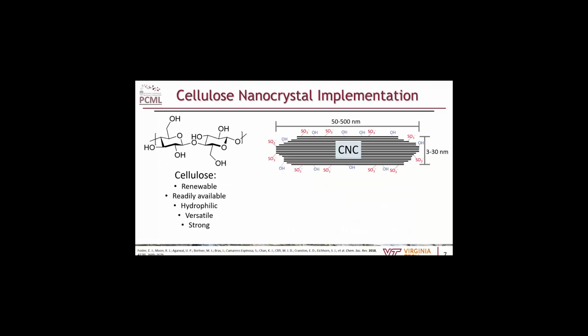To take a closer look at cellulose nanocrystals, which is more the focus of my talk today, we can look at all of these stacked layers that build up. If you use an acid like sulfuric acid to hydrolyze away the amorphous sections, you'll end up with these charged sulfate half esters, as they're called, on the surface. This allows the cellulose nanocrystals to repel each other, so they're fairly stable in an aqueous suspension, with very little aggregation or sedimentation.